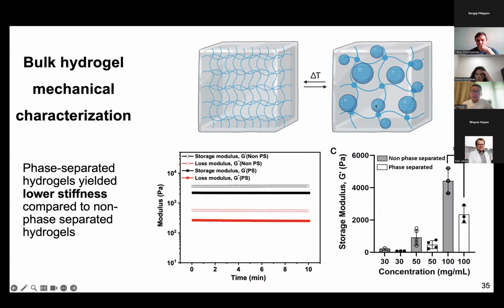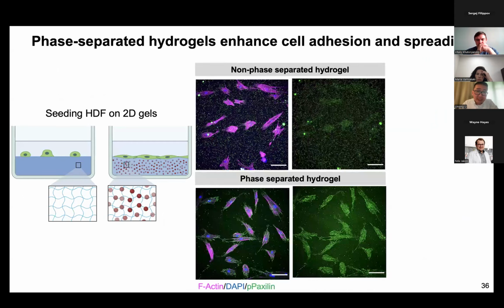So we're now trying, this is a bulk hydrogel stiffness characterization. We're trying to use AFM to really characterize the local regions of the mechanical properties. And then when we do these 2D cell studies, we see that the traditional concept is that stiffer substrates promote better cell adhesion and spreading. And again, our data shows completely the opposite results.